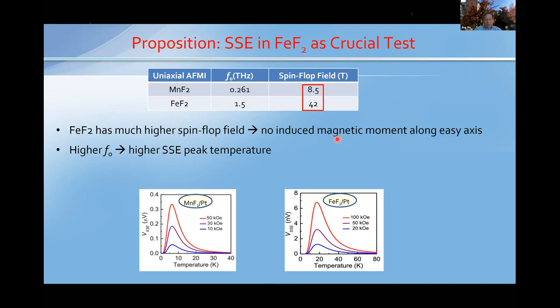A little more quantitative test is the magnon frequency in this iron fluoride, which is connected with the fact that the spin flop transition field is high. Because of the high frequency, according to the model that I described earlier, one would expect the peak position to be located at a higher temperature compared to, let's say, manganese fluoride. So these are theoretically predicted and plotted below.